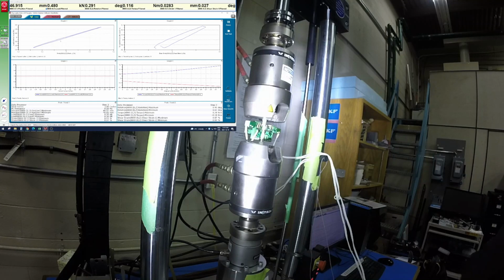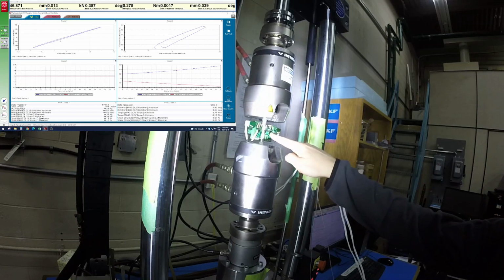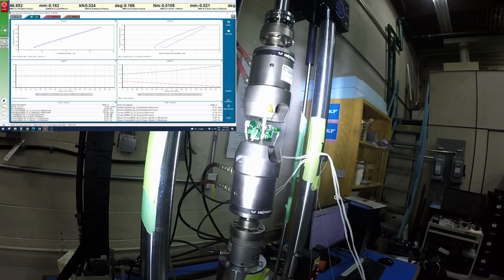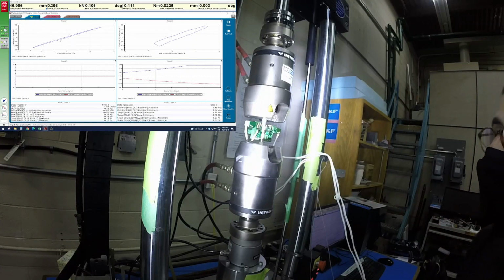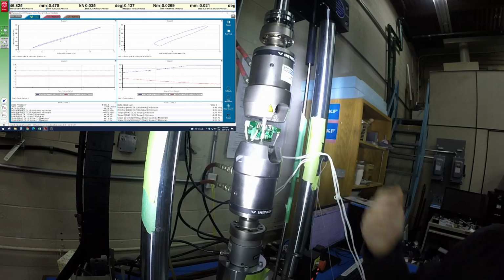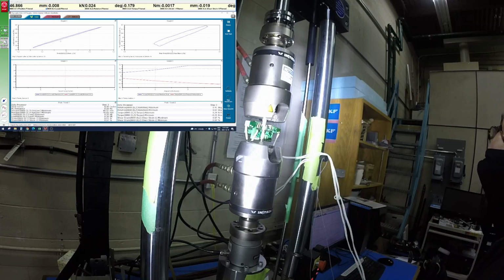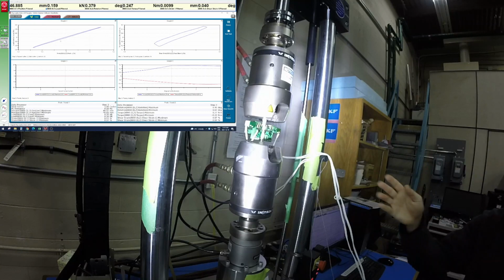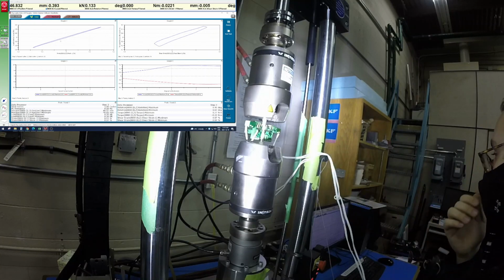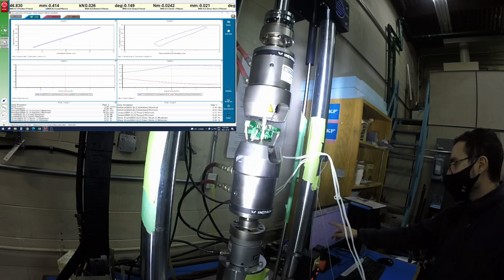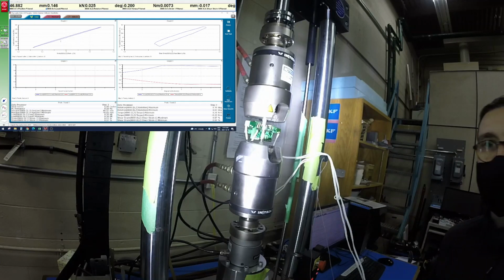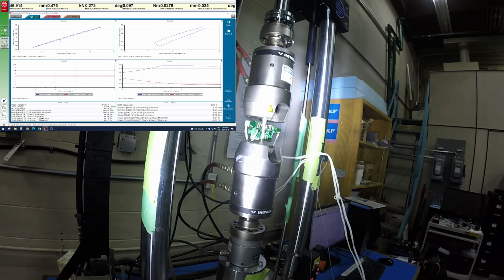So the shear actually is getting influenced by the fact that I used a failed sample here with a small crack in it for this video SOP to demonstrate the type of data that you might get in a situation where that's occurring. So we have some area here. We can show some area in the hysteresis of the shear strain, and the axial strain pretty much looks as you would expect for a low amplitude test.